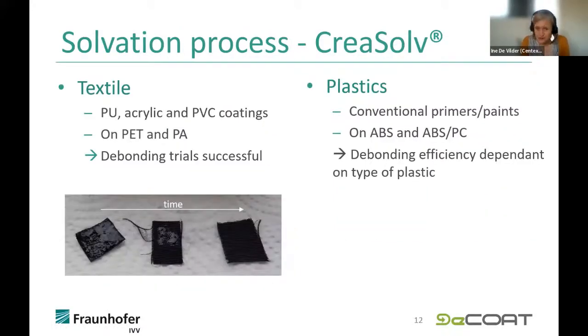Yes, we also use the Creasolve process, which was mentioned before by Martin in this project. We did some testing on PU, acrylic and PVC coated textile. We used polyester and polyamide, and we have very nice results on this. In all cases, the coating could either be dissolved, as you can see on this picture, or delaminated. So we always end up with a quite clean, pure textile in the end. For the plastics, we did testing with conventional primers and paints on ABS and on ABS-PC. Here we saw that the debonding efficiency was dependent on the type of plastic. So from one plastic to another, the process needs more fine-tuning. So it was a little bit more difficult than the textile.